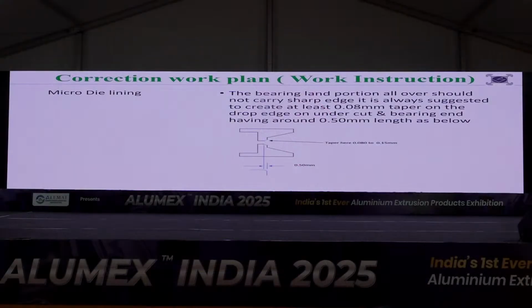That is the die bearing, and we see a taper line, and we see the undercut and further taper. The first taper is to drive away the built up from the dies, billet after billet. But if the bearing edge is not a little tapered, then what happens?